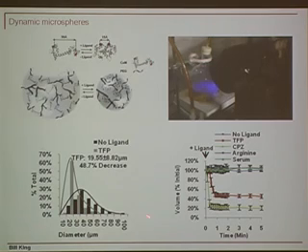If you look at quantitatively the volume shift in response to a variety of different environments, you can see that in the absence of ligand, this blue curve here, there's essentially no change in volume of these hydrogel microspheres over time. In the presence of arginine, which is a positively charged molecule that's similar in charge to trifluoperazine but different in terms of its ability to interact with calmodulin, so it's a nice control, we see a flat line again, no significant decrease. And then importantly, in the presence of serum, we see no decrease in volume of these materials. So this is important, suggests that the interaction, the collapse of calmodulin and that of the network is biospecific. It's not happening in heterogeneous solutions.